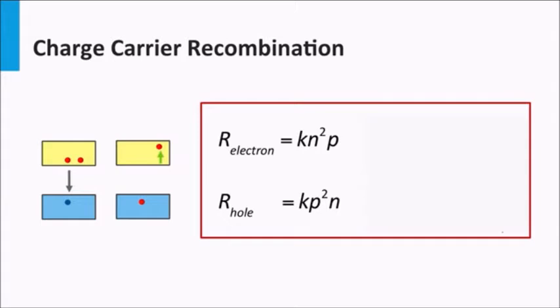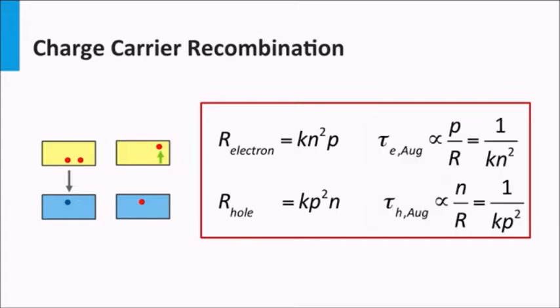The R electron is dominant when the electrons are the majority charge carriers, whereas R hole is dominant when the holes are the majority charge carriers. In a simple approximation, the lifetime is 1 over the density of charge carriers squared. As a consequence, Auger recombination becomes dominant in photovoltaic materials with high densities of charge carriers, like in highly doped crystalline silicon, or solar cells under strong illumination, like concentrator solar cells.